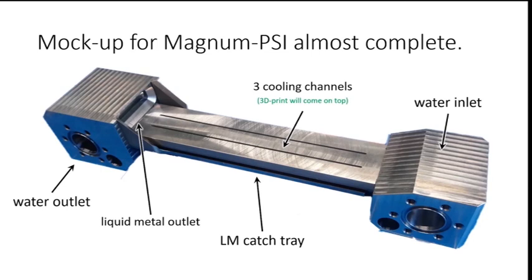There are already papers that you can find for how that works with lithium in some kind of porous substrate, not the 3D printed one, unfortunately. And the lithium one seems to perform fairly well. As far as I know, there is no damage as long as you make that substrate out of tungsten and not of anything else. Now the question is, will that work with the 3D printed samples, and will it work with liquid tin?